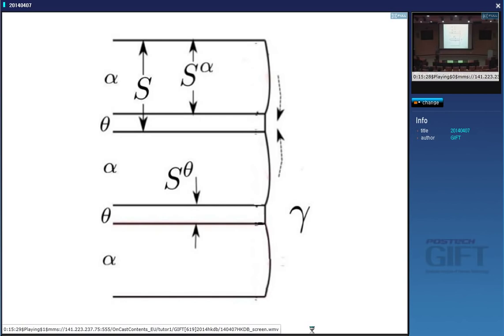Everyone happy with that? So it's totally different from the single phase growth that we considered earlier, where you build up carbon ahead of the interface. Here, the carbon that is partitioned into the austenite by the ferrite is absorbed by the cementite. And this is the meaning of cooperative growth. The composition of the austenite away from the interface does not change, right? At least for a binary alloy, it does not change, okay?